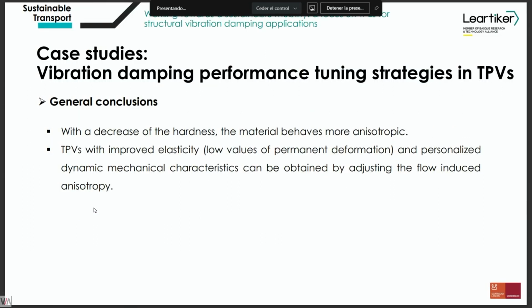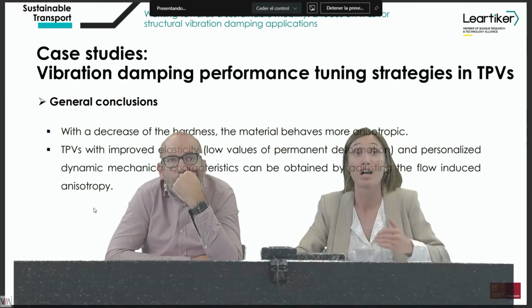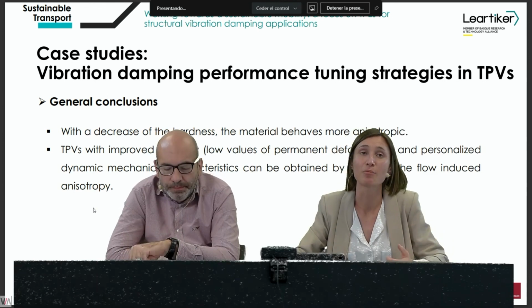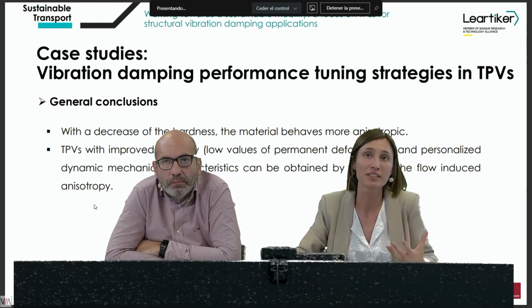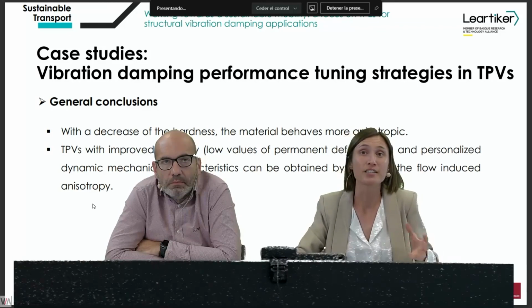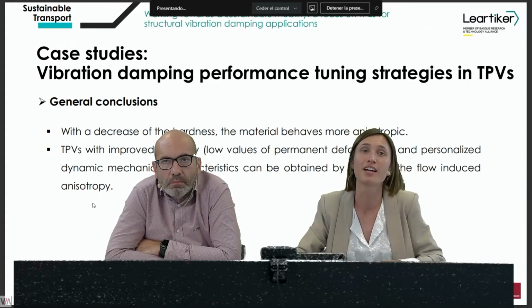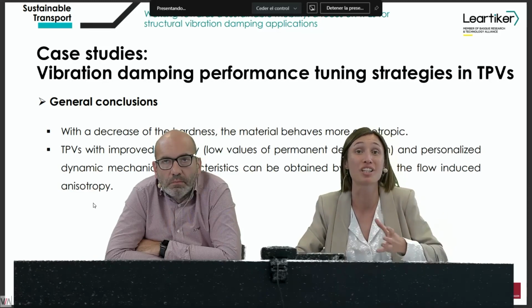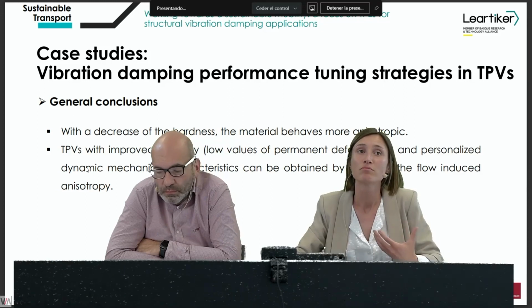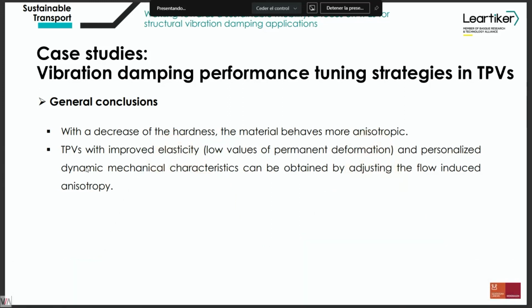So the main conclusion in this second project was that, as we saw, with decreasing hardness, the material is more anisotropic. That means that in these Shore A60 materials, we are able to tune their performances, not only static, but also dynamic mechanical properties. And so we think that there is room here to research and to improve the performances of TPV materials, improve their elasticity in terms of low values of permanent deformation, and customize the dynamic mechanical characteristics by adjusting this flow-induced anisotropy. So somehow controlling the processing and the microstructure.